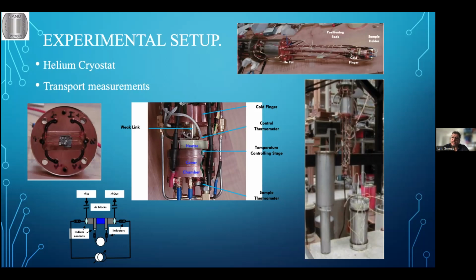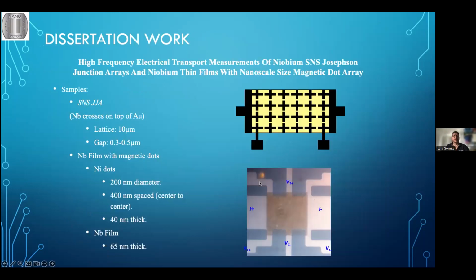And we do this using the 4-probe method. For example, through this electrode on this side of the sample and this side of the sample, we send current, and then through these two electrodes we measure the voltage. This is called the 4-probe method. And also, to measure superconductivity, you have to cancel.